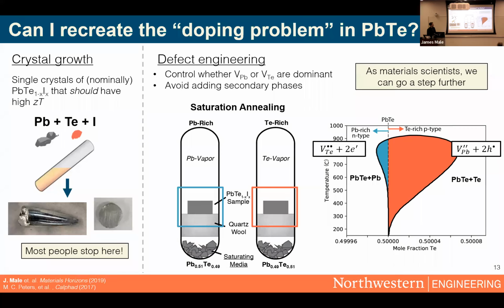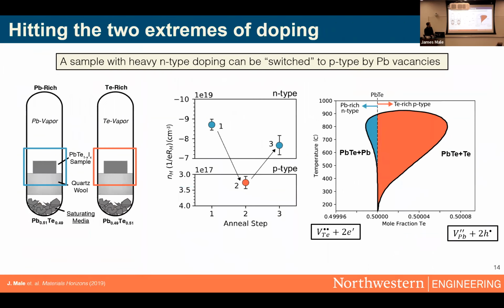And by definition, when you're in a two-phase region, the matrix composition of, say, lead telluride in this case will be fixed entirely to the lead-rich side or the tellurium-rich side, depending on how you saturation anneal. So using that technique, I demonstrated that we can flip back and forth across a phase width with a relatively simple strategy. I demonstrated this using some iodine-doped lead telluride that I saturation annealed to lead-rich conditions, which gives me really good N-type performance.